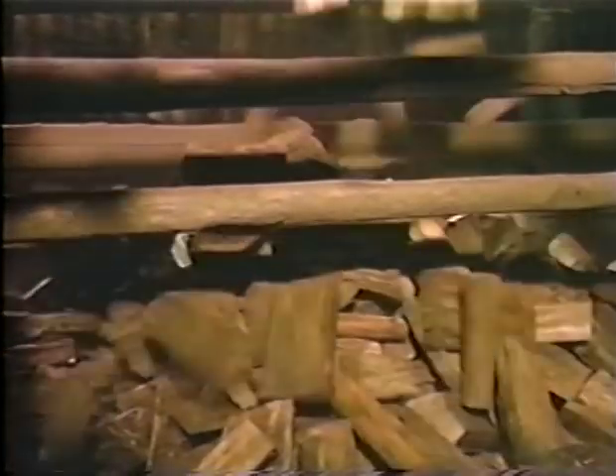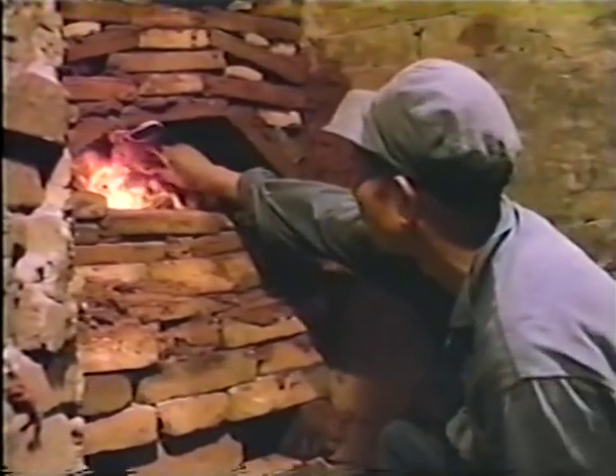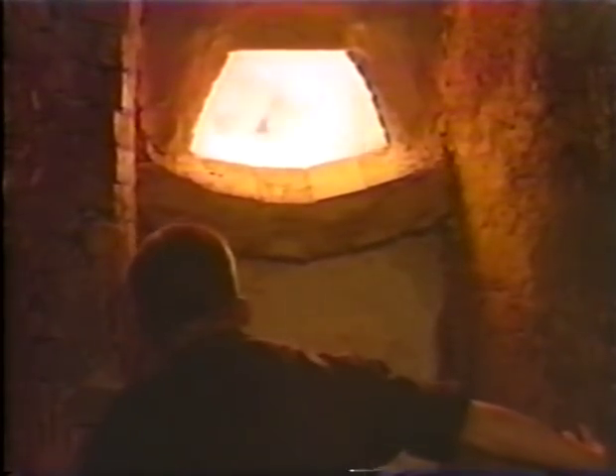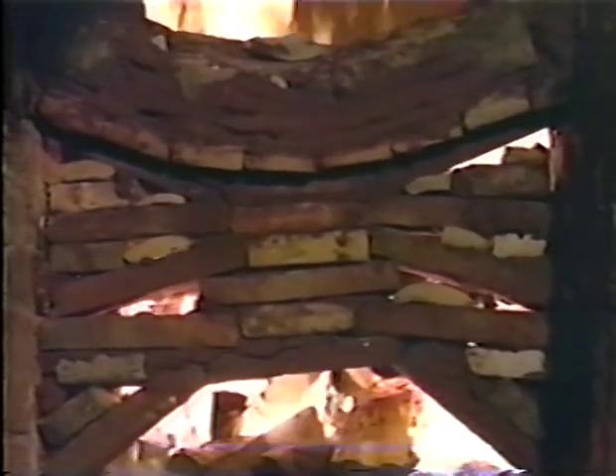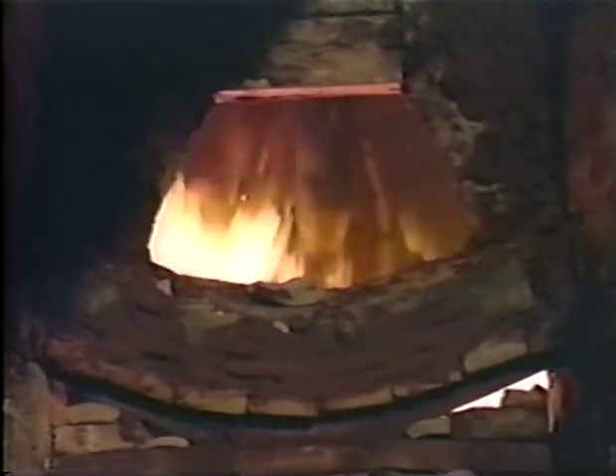In the past, the kilns at Jingdezhen were fired with wood as the fuel. Today, oil-burning kilns have replaced the wood-burning ones, except at this workshop where the former method is preserved. Workers continuously feed firewood into the kiln as the temperature slowly climbs to 1,250 degrees centigrade. Workers at the imperial kiln had no mechanical devices to measure temperature; the kiln specialist gauged it by watching the flames gradually turn from red to bluish white. There was little room for error, and the success of the entire process depended on a proper firing. Prayers were offered to the kiln god before the firing began.